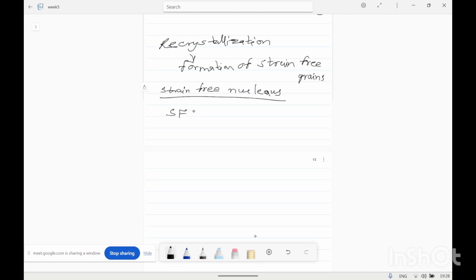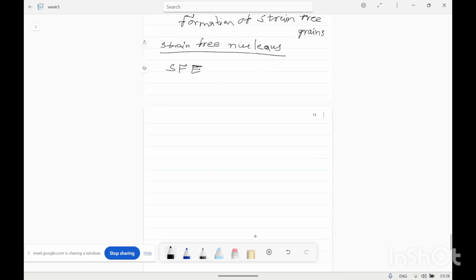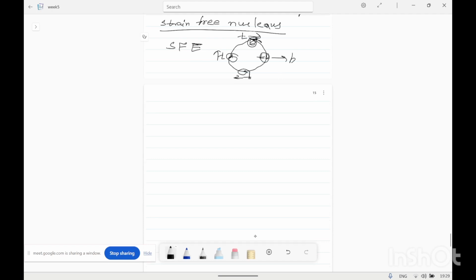So how does stacking fault energy contribute to the recrystallization process? If we see a dislocation loop, the Burgers vector is on this side. If we see the line vector along the loop, in this direction the line vector is parallel to the Burgers vector, so it will be of screw character. At this point the line vector will be perpendicular, this parallel, and this perpendicular. At these edges the dislocation is of edge character, and at these edges the dislocation is of screw character.